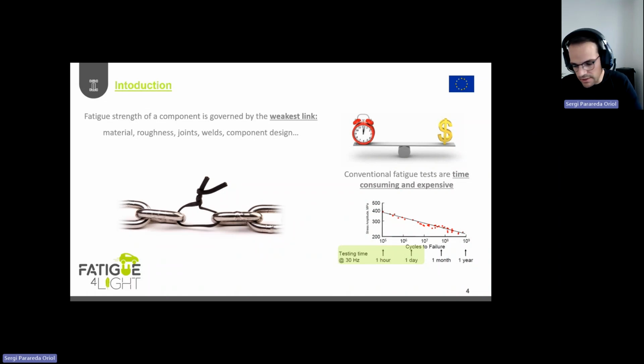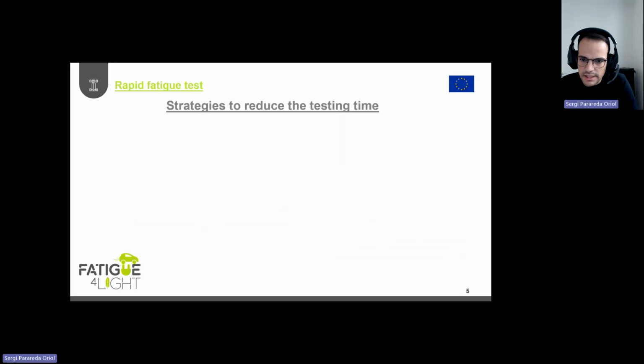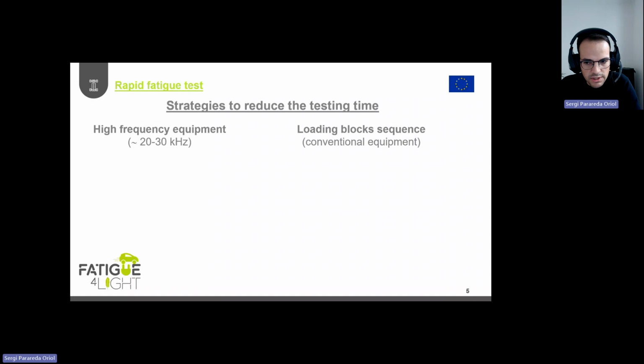By considering all of these different points, as already mentioned, fatigue tests are time-consuming and also expensive. So there is a need to obtain new strategies to reduce the testing time. As Lucia mentioned, in the Fatigue4Light project we have two strategies. One strategy is to use high-frequency equipment, so we can reduce the testing time by increasing the loading and unloading frequency of the specimen. In this case, we can reach up to 20 to 30 kilohertz, which is a huge reduction of the testing time. And we can also use a loading block sequence.